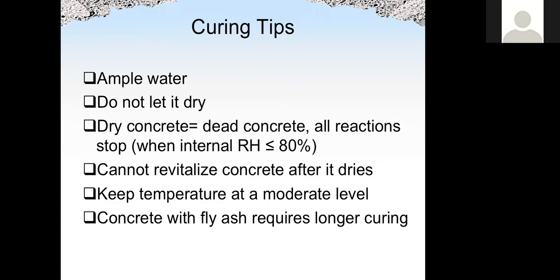For temperature, moderate temperature is the best. Room temperature around 75 degrees Fahrenheit, 23 to 24 degrees Celsius, will be the best. If the temperature is too low, below the freezing temperature, the concrete will freeze. If the temperature is too high, we may have delayed ettringite formation, flash set, and so on. If the concrete has fly ash or slag, it will require longer curing, because fly ash and slag are pozzolanic materials. And the pozzolanic reaction requires longer curing time because that reaction is slower compared to hydration of cement.